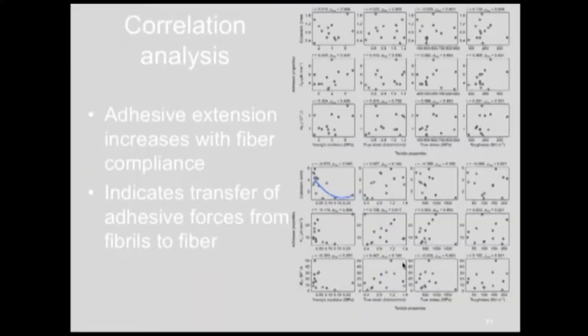In our wet conditions, with performance of adhesive and tensile properties, we see that just adhesive extension and stiffness or compliance are pretty well correlated, which would indicate that when wet, both tensile properties of the axial fiber and extension of the thread itself are quite closely connected. This indicates that that compliance that I showed you is important, and it indicates some degree of transfer of those forces from the fibrils to the fiber, meaning that everything is working together. The fibrils and the fiber are operating together, allowing for forces to be transferred rather than isolated to the fibrils. This would improve the overall performance of these threads so that when they're being used by spiders in webs, they can be better able to catch the prey that they're encountering.